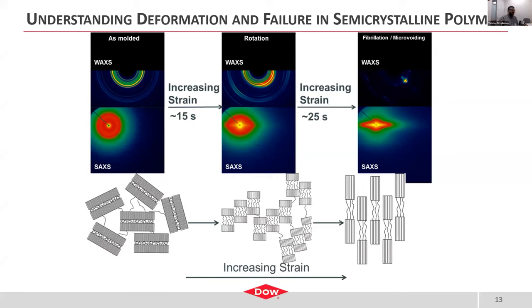in the intensity of the small angle X-ray scattering. That sharp increase in intensity is due to the actual formation of microvoids and crazing artifacts as the material is being ripped apart. You get small pinhole voids. So now your scattering signal in the small angle is much more intense in those final few seconds before total failure. So we know how a semicrystalline polymer deforms. So what do we do to increase the toughness?